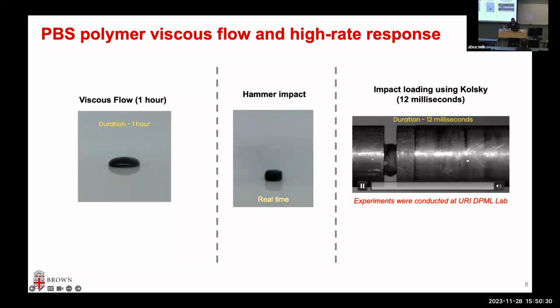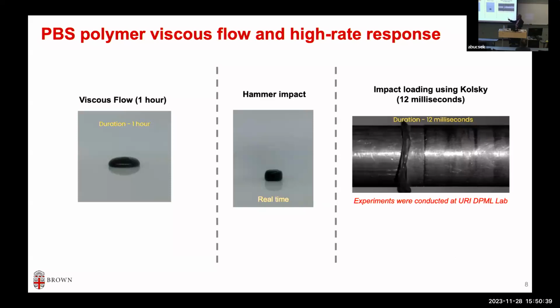But Kolsky bar is a very high rate experiment in the laboratory. You have two bars, you squish the sandwich and hit with a very fast projectile on one end that causes a stress wave to propagate. So this video is going from hours to seconds to milliseconds, or 12 milliseconds.